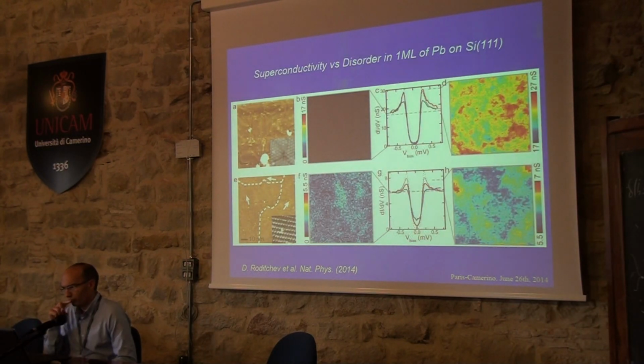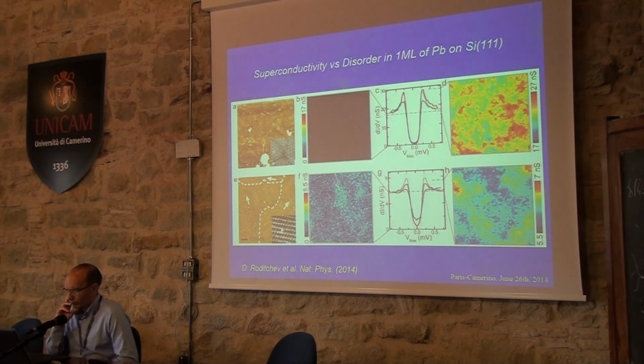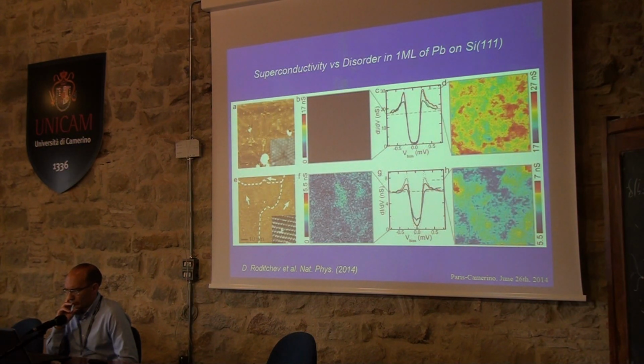So, this is a very interesting result in which we compare the superconductivity in the striped incommensurate structure, which is the upper part of this slide, and this square root 7 by square root 3 structure, which is the bottom part. On the striped incommensurate, you get a superconducting gap. You can clearly see, and the superconducting gap is spatially very robust.